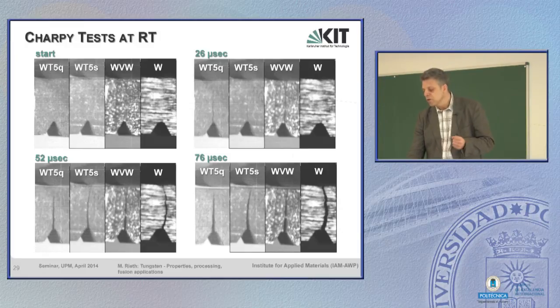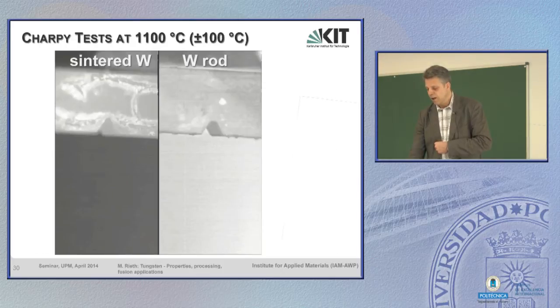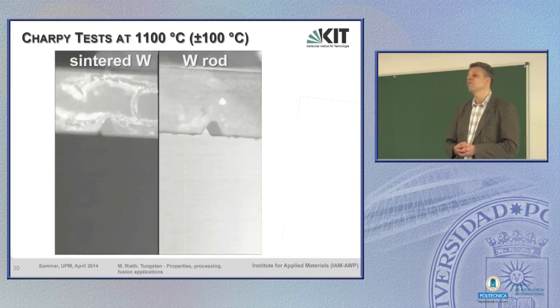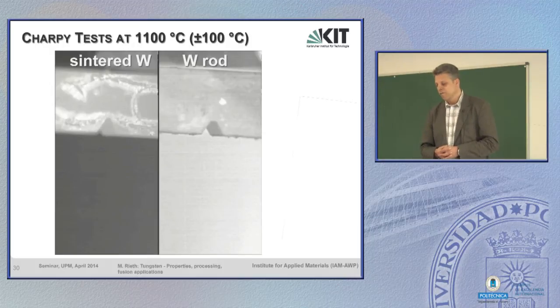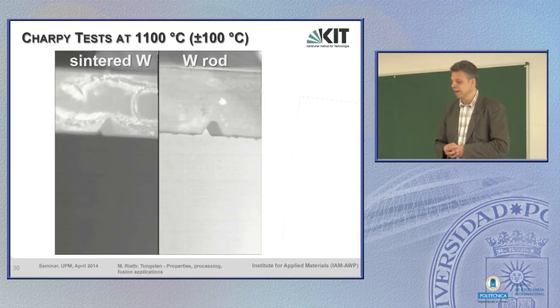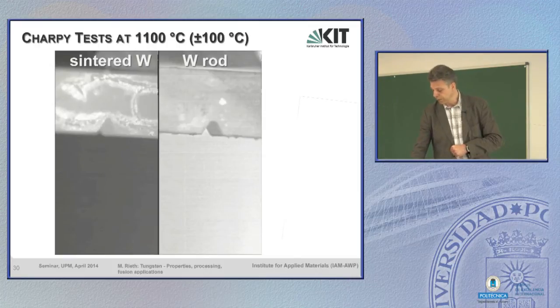Now the question is, where do we see the ductile to brittle transition temperature? We make a jump now up to 1100 °C, and on the left hand side you see sintered tungsten, and even at 1100 degrees centigrade the material doesn't change its behavior. It still shows fast fracture. But the tungsten rod on the right hand side, you see, behaves as we know it from steel. At moderate temperature, it's a ductile fracture without fast crack involvement.